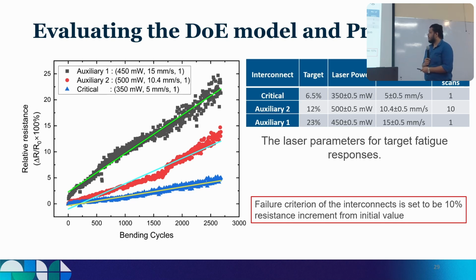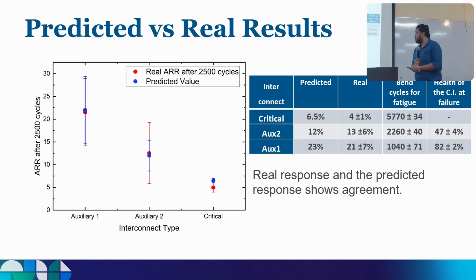And this is the result of those three resistances for those three parameter sets. You can see that the green line is the auxiliary one, which has the most increment, and so on. Finally, this was my result. After real analysis, I achieved values almost inside the predicted ones. For the critical interconnect I predicted 6.5%, but I achieved 4%. That's even better. And for the auxiliaries, I achieved very close increments of resistance.